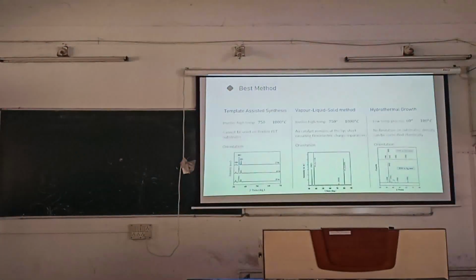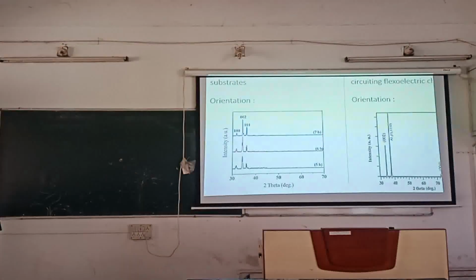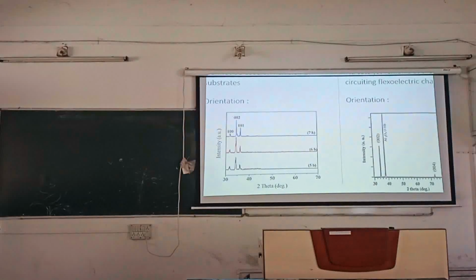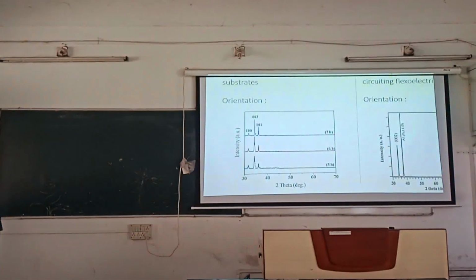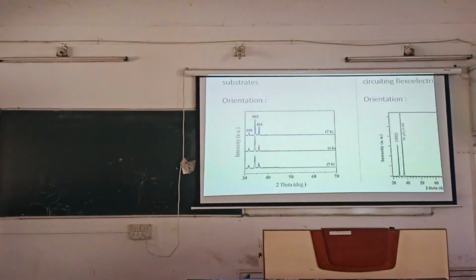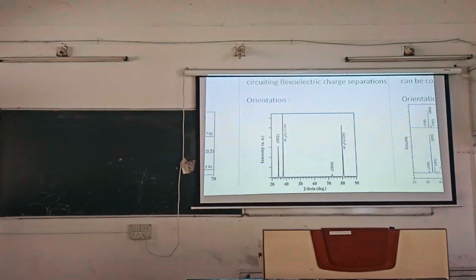So comparing all the methods and comparing the X-ray diffraction data of all three methods, we see this is for the first one. The 002 peak is what we want, other two peaks we don't want. So there is a significant amount of zinc oxide which is oriented in other directions. Here it is very less, but there are other peaks of other atoms, Al2O3 and all. The silica peaks are there.